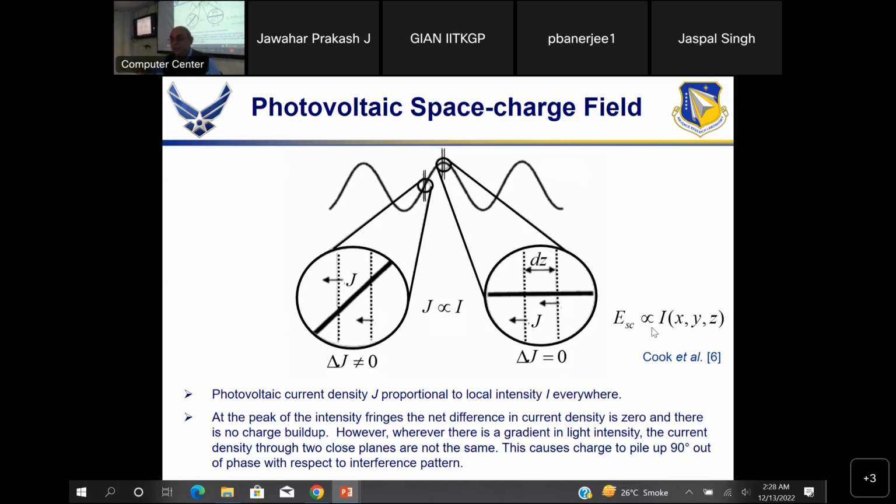So that being the case, if someone asked me, what crystal would you like to use to amplify a light beam? I would not choose lithium niobate, because lithium niobate having a large photovoltaic effect, there is not much energy coupling between the two beams. There is a lot of phase coupling between the beams, but there is not much energy coupling between the beams. Are you understanding this? Okay.